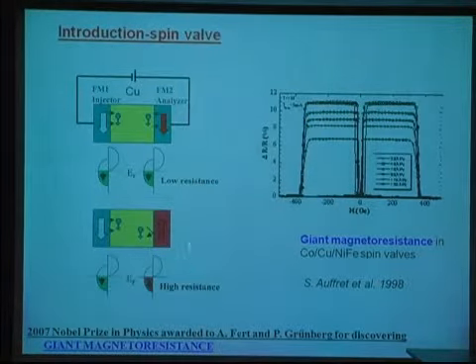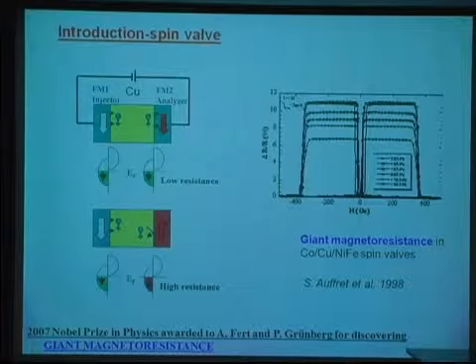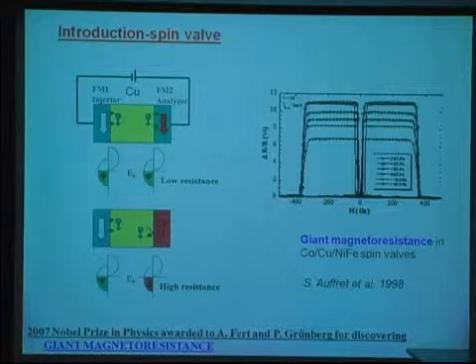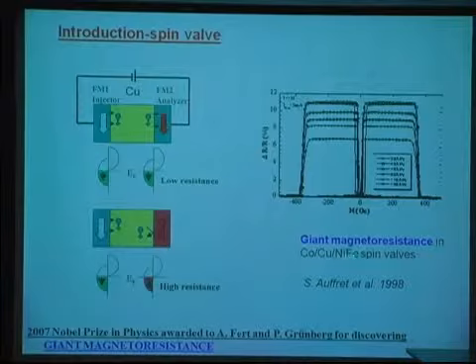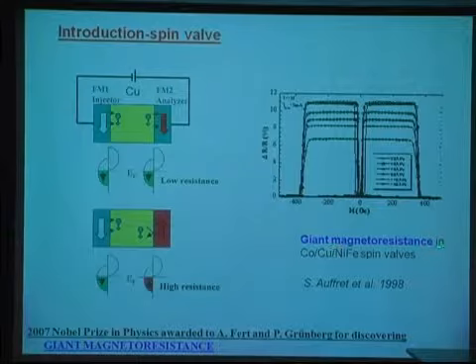But in the other case, if we don't have any density of states for the spin at the second electrode, what happens in this situation? The spin has to reflect back. This brings the high resistance of the device. Okay, so this is the magnetic response of this giant magnetoresistance, with copper and nickel iron as the spin injector and detector. And this is the giant magnetoresistance.